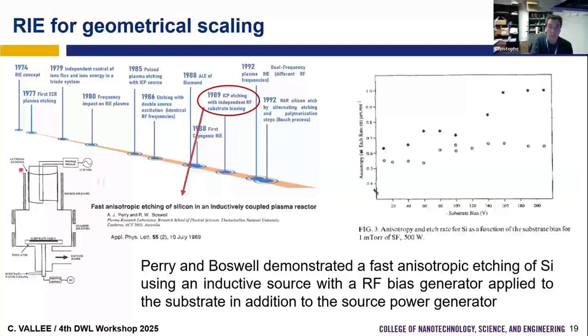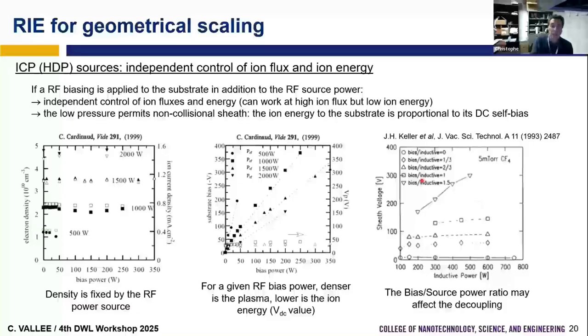So now we have inductively coupled plasma reactors, where we make the plasma thanks to the inductive field and not the capacitive field. And we have an independent bias of the substrate. So we have two powers, one for the plasma density and one to control the ion energy. Then we may have very good anisotropic etching. They were the first, to my knowledge, to demonstrate this fast anisotropic etching with an independent RF substrate biasing. And this is the idea of all what we call HDP sources or inductive sources, because it's mainly inductive, but a microwave system can be put in the HDP source, where we have now an independent control of ion flux and ion energy.